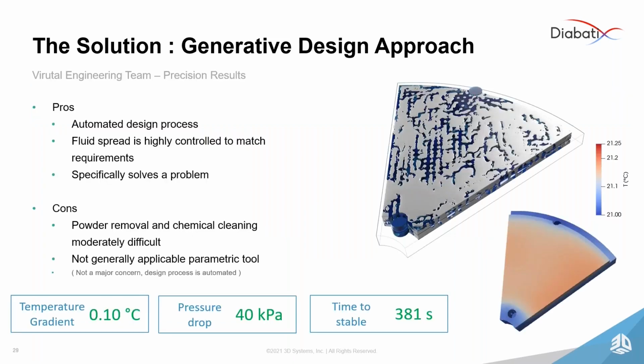Let's have a look as well at a summary of the results and evaluate again the same 3 key parameters. Let's start with that. So the thermal gradient was at 0.10 degrees Celsius. It's a little bit higher than what you had with the serpentine design, but your system couldn't handle that one because of the too high pressure drop, and still the thermal gradient is within the acceptable range. Pressure drop is at 40 kilopascal, so also within the acceptable range, and time to stable is at 381 seconds, which is significantly lower than what we have seen so far. So if you would compare it with the 2 other designs with the conventional method, this is the only design which fulfills all your